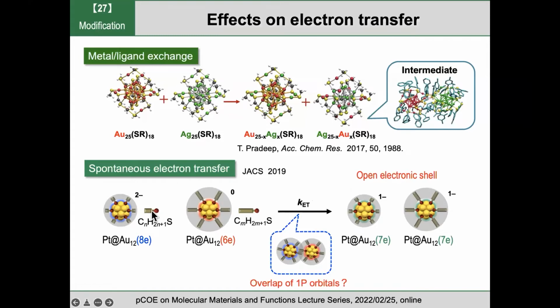So maybe this is the opposite of our expectation, because this layer is an insulating layer. But we think that the lifetime of the dimer is important for this electron transfer, and we think that the lifetime of the dimer is enhanced by the increase of the chain length due to the weak van der Waals interaction. So now we are studying the effect of chain length on the electron transfer.